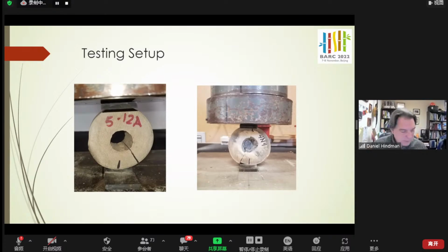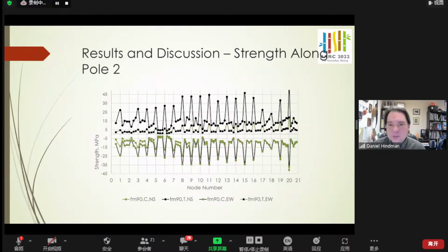Now, I said we tested some 600 samples as we did this with 8 poles, and data analysis then became our main challenge. And so here are some of our results. This is the strength in MPa along the pole. There are 4 different strengths given for tension and compression in the north-south and tension and compression in the east-west. The north-south would correspond to the top and bottom, and the east-west to the left and right. What you're seeing here is the complete pole. So the points that are much higher or much lower correspond to the nodes versus the internodes.